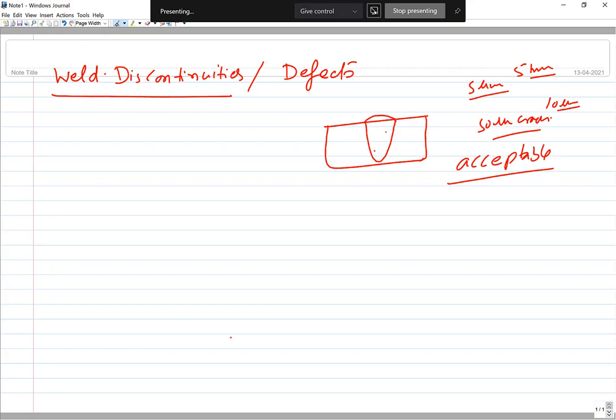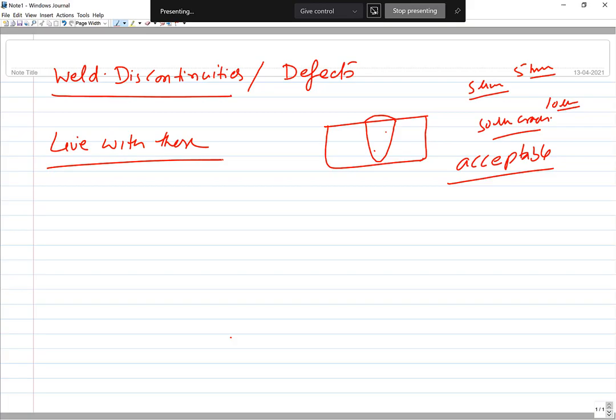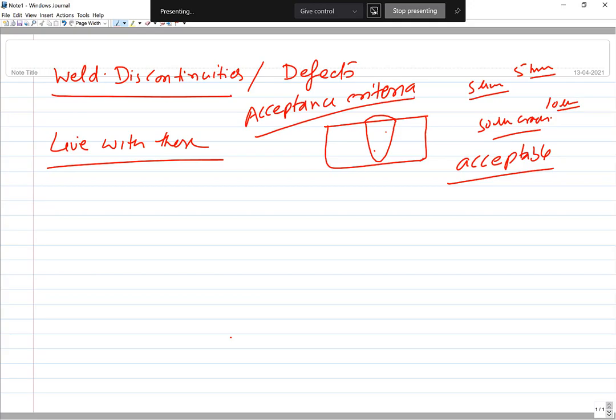We have to live with these discontinuities, so we optimize welding-related parameters such that these are within acceptable limits. You need to control your process so that discontinuities do not go beyond acceptable limits. That is why you will always find acceptance criteria with regard to weld joints — what size can be accepted depending on section thickness. For a weld in a 50 mm plate, a 1-2 mm crack may be non-propagating and may not harm the joint in any way.